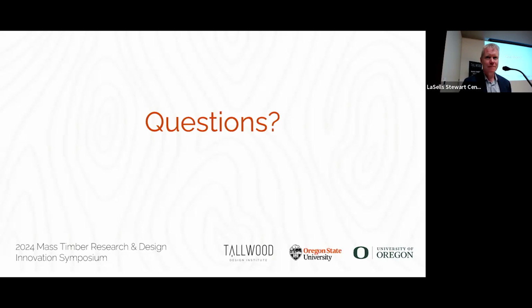So yeah, OSU is unique in that we have 3 structures laboratories on this campus, right? You're going to see 2 of them today, but there's also the civil engineering structures lab out at Hinsdale, and it's an industrial building, covered, but we don't have any conditioning per se inside the laboratory, so it's going to get heat changes during seasonal changes, even daily, and the relative humidity is uncontrolled. At the end of it is where the whole plank beam specimens that I showed for the creep tests are. They're going to be subjected to whatever the ambient conditions are in the laboratory. We've got environmental sensors measuring relative humidity and temperature locally where those specimens are located.